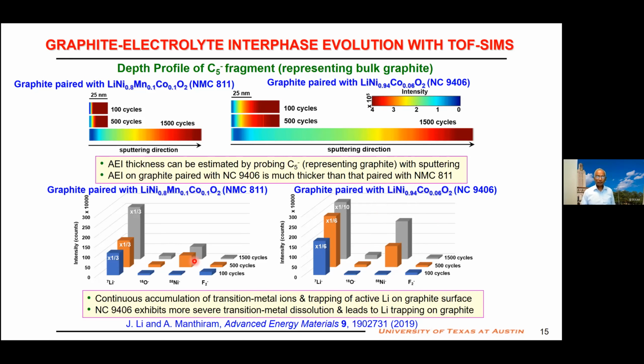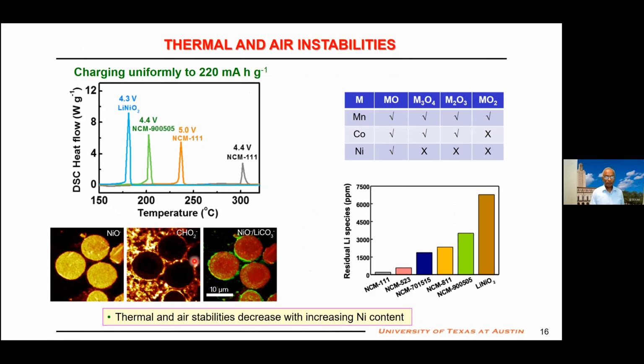So we can understand what is happening. Metal dissolution is a problem that can degrade the cyclability of the cathode, but largely of the graphite anode as well. Now I talked about the second problem, thermal stability. As you see here, when we increase the nickel content from 30% to pure nickel, the thermal stability is decreasing. They release oxygen at a lower temperature. That will lead to safety problems. And that is not linear. It is actually exponential.